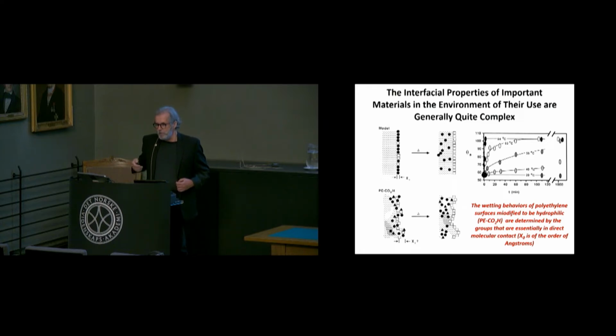These materials could restructure in ways that led to enormous complexity, and what's shown is changes in wetting data, the contact angle as illustrated by the drop that I showed you on the slide before, as a function of temperature and time. And you'll notice that the surface properties change relatively abruptly, going from hydrophilic to hydrophobic, extremely hydrophobic, even heating at a modest temperature for a brief period.